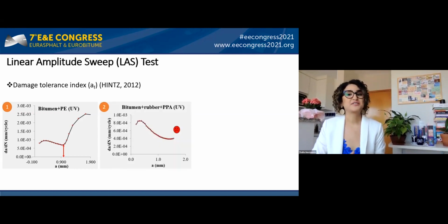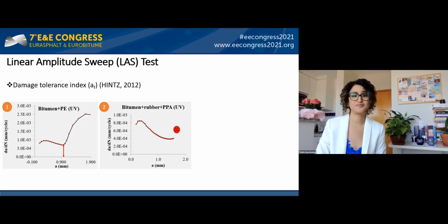However, some materials could not be determined using the Af index, as we can see for the UV aged bitumen plus rubber plus PPA in the curve of figure 2. A possible explanation for such limitation, according to the literature, is the occurrence of adhesion problems between the sample and the metal plate, or the predominance of flow over the cohesive fracture due to fatigue.